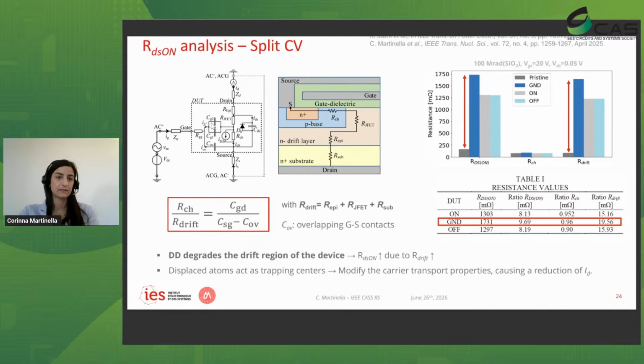So you start from the equivalent circuit of a power MOSFET, and by solving the Kirchhoff system of equations, it's possible to retrieve a relation between the channel resistance, so the resistance of the channel of our device, and the drift resistance, where this drift resistance is due to the sum of the epitaxial layer resistance here, the JFET resistance, and the substrate one. And so you can retrieve this relationship where the gate-drain capacitance and the source-gate capacitance are involved, and also the overlapping capacitance between gate and source contact.